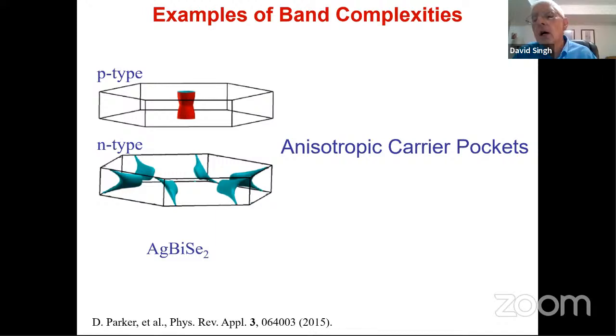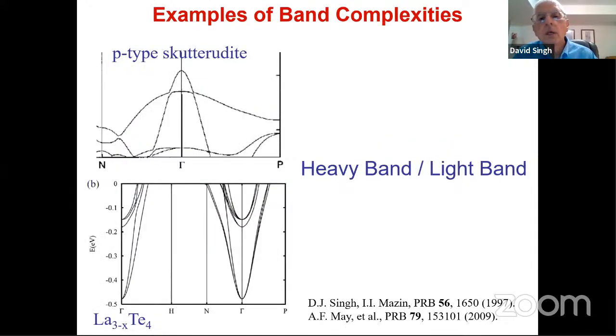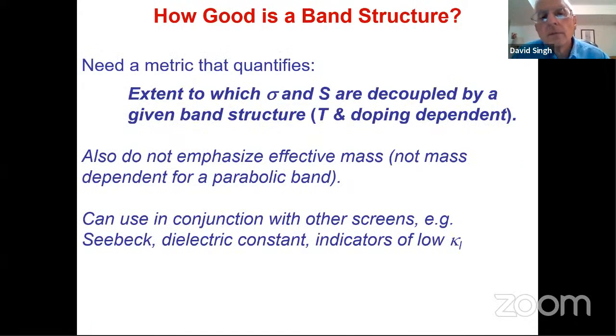So what's better than what? How do we know? And so here are some other mixtures. We wanted to have a metric. And what do we want to measure? So we saw the problem of thermoelectrics was this contraindication, so that sigma, the conductivity, and the Seebeck coefficient are coupled, because in a parabolic band structure, they're tied together. So we want to have a non-parabolic band structure, and we want to figure out the extent to which these quantities are decoupled in a given band structure. And we want a metric that depends on temperature and doping level so that we can optimize those things.